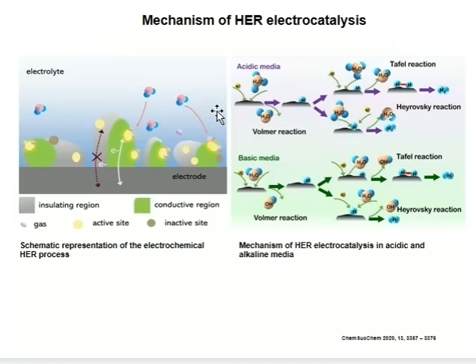The hydrogen evolution reaction often occurs via the Volmer-Heyrovsky route or the Volmer-Tafel route. During the hydrogen evolution reaction, hydrogen atoms are adsorbed on the surface of the catalyst through the Volmer reaction. Then hydrogen is released from the interface through the Tafel reaction. If the kinetics of the desorption process is slow at room temperature, the Volmer reaction will be the rate-determining step.